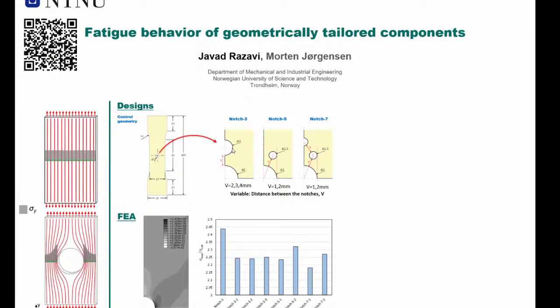Where we had one added notch on each side, by changing the distance, the maximum stress didn't change significantly. The changes were quite small, and that was somehow disappointing for us. But for the other two cases, by increasing the distance, we had higher stresses. So obviously we could see that when the notch is closer to the main notch, it's affecting it more. But this was the stress analysis. We couldn't get any conclusion from it.